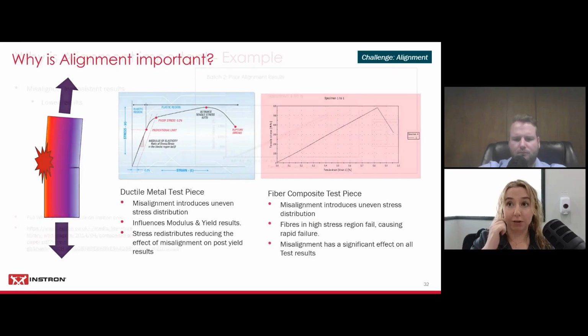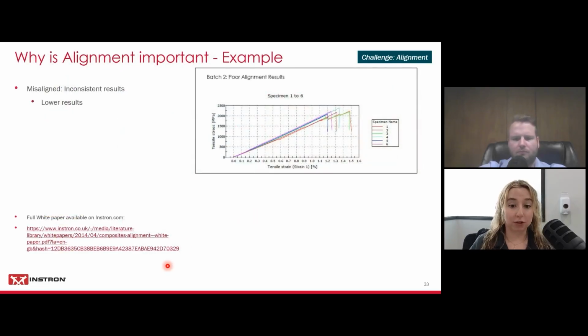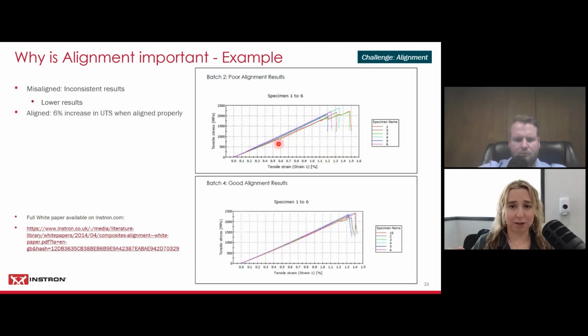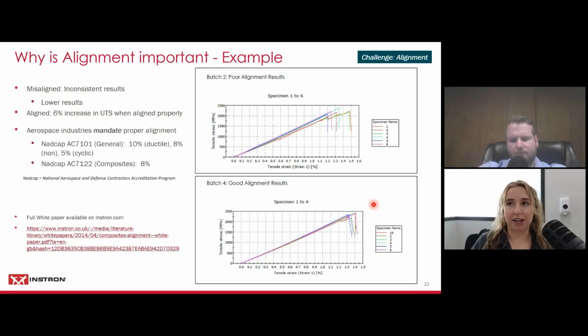And we have an example of how significant this can be. A couple of years ago, we did an internal study where we loaded some composite specimens into a frame that we knew that the grips were not perfectly aligned. You can see in the graph on the right, we have a pretty big distribution within the stress strain curve, as well as a pretty big distribution when it comes to that tensile strength and our ultimate tensile strain. Now, we then aligned the frame, which I'll talk about later about how we do that. And we can see that deviation within those curves is significantly lower. Our ultimate tensile strength deviation is significantly lower. And we actually saw that our ultimate tensile strength increased 6% after we did proper alignment. That might not seem like a lot, but that could be the difference between shipping or not shipping a product. And we also saw that our tensile strain increased as well.